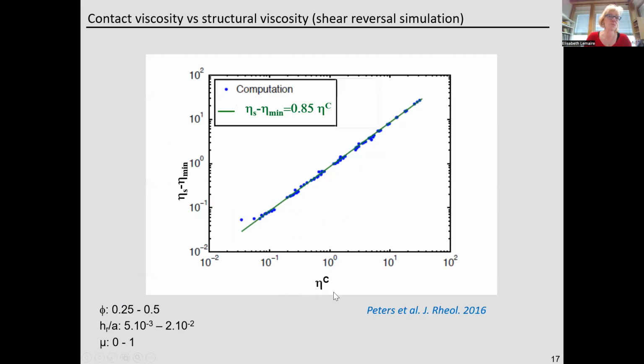And it can be important, for instance, if you want to formulate a suspension, usually with a low viscosity. It's more interesting to measure the contact viscosity, or more or less equivalently the difference between the steady and the minimum viscosity, than the global viscosity. Okay, the effect of the contact properties of the particles will be seen more sensitively. Okay, so Elisabeth?